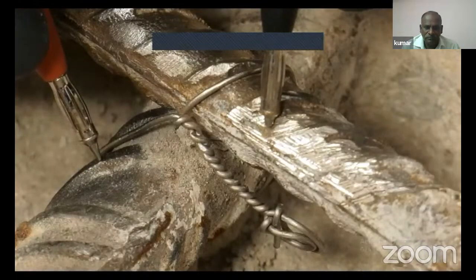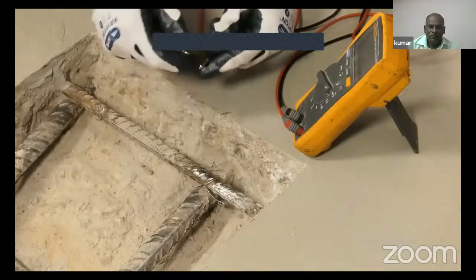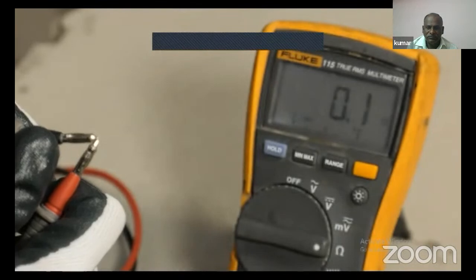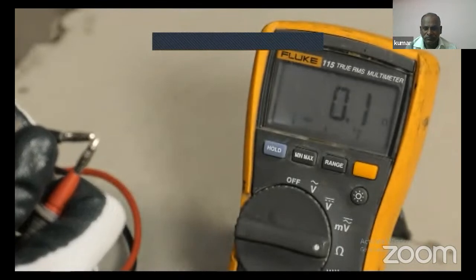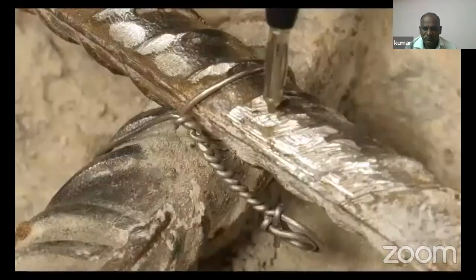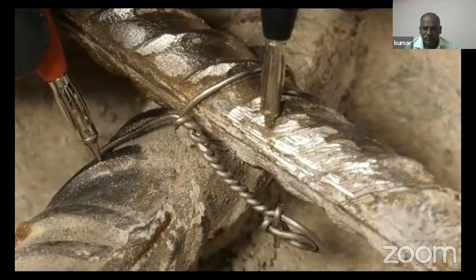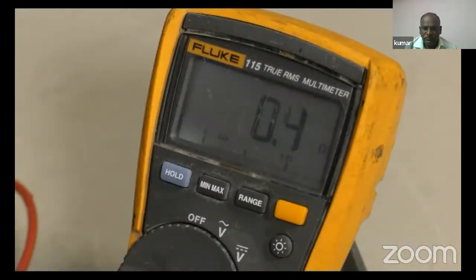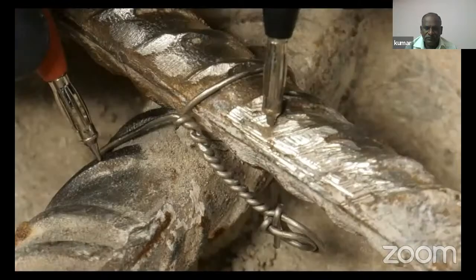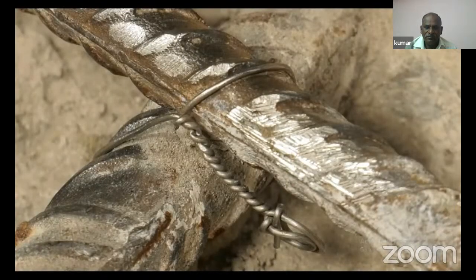Then confirm steel continuity in areas to be treated using a high impedance multimeter. Check the resistivity of your meter and cables prior to use and subtract this value from the figure that is read to give a true reading. The resistivity should be 1 ohm or less. If this is not the case, metal tie wires can be used to connect the reinforcing bars to achieve the